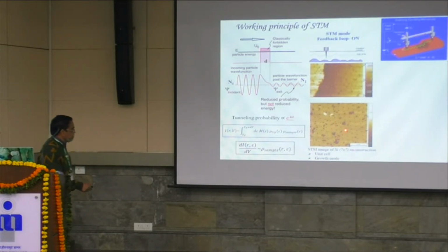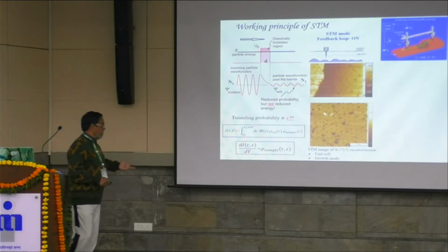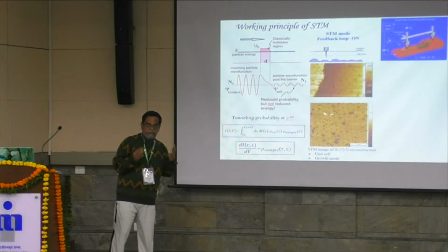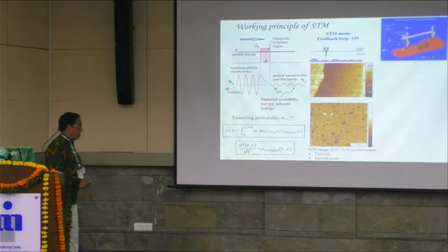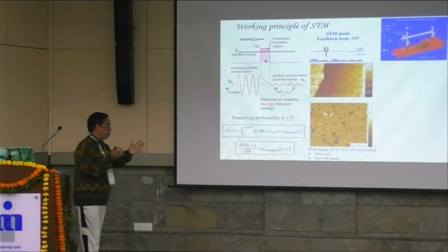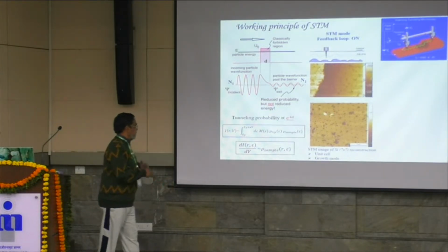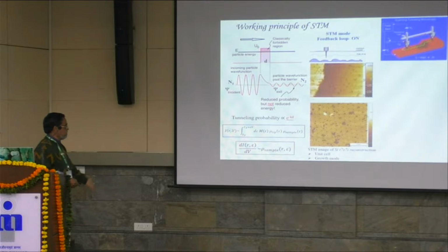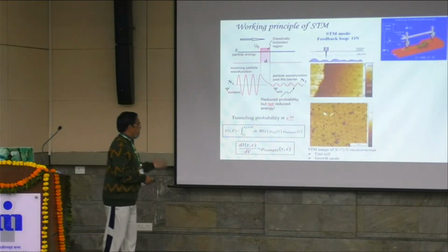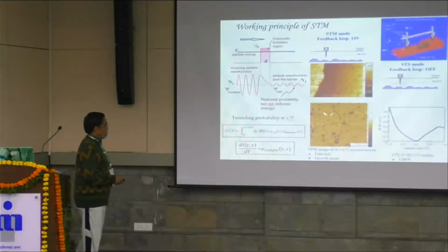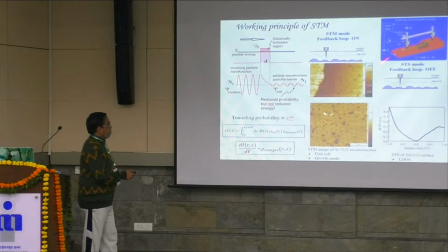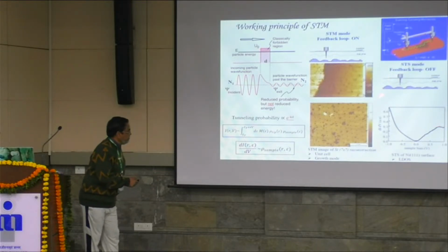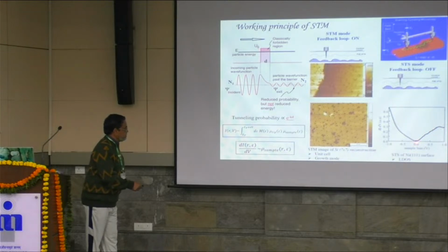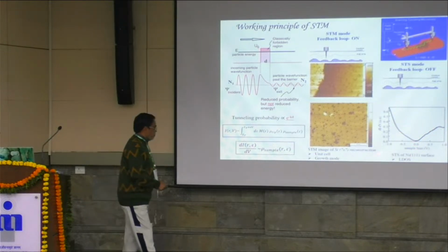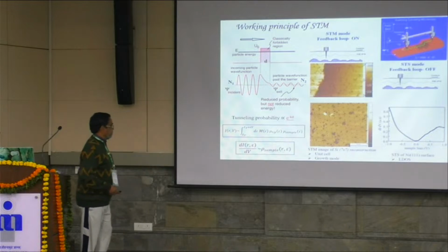And so this is the atomic resolution image, and you can see these silicon atoms, and this is the way STM helps to determine the surface structure of the 7x7, because the unit cell is 7 times in both directions compared to the bulk silicon, and the structure is much more complicated than the bulk silicon. And so STM helped to solve this silicon 7x7 structure. In the STS mode, the spectroscopy mode, the feedback is off, and one can get a local density of states. The 0 is the Fermi level, with occupied states and unoccupied states both around the Fermi level.